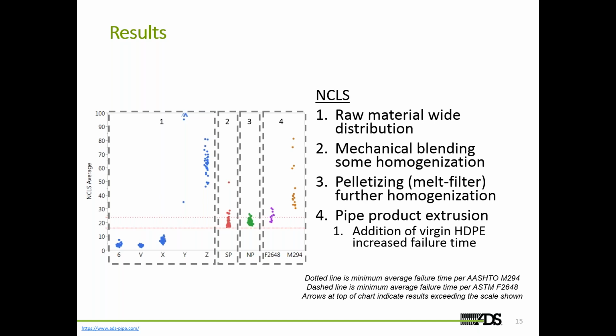Here's the results. Some things that I think it's wise to point out. When we're looking at our different raw material streams, the 6 down in the bottom left-hand corner is indicative of post-consumer recycled material. As you can see, it's a rather poor performing material. When you're looking at stress crack resistance, the 2 red lines on that chart that are going horizontal are the minimum values that are required for both the ASTM F2648 product and the AASHTO M294 product. AASHTO M294 actually requires a higher NCLS value, so that's why one line's above the other. But as you can see, the post-consumer recycled material is actually a fairly poor performing raw material when you're looking at NCLS.